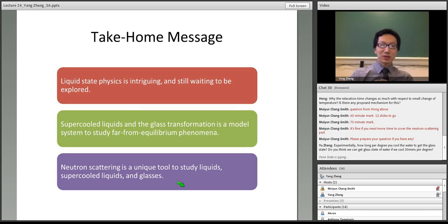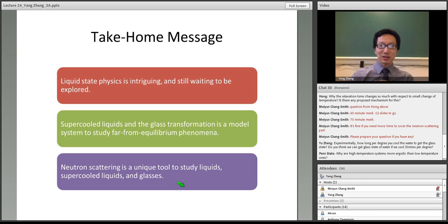So what we were doing is actually, since we just listened to Jin's nice lecture, we're trying to locate whether there's a second liquid-to-liquid critical point in water. Based on his theoretical predictions, the second critical point lies in the region of the phase diagram, the so-called no man's land, below the homogeneous nucleation. So there's no way for us to maintain supercooled water experimentally in that region. So we use nanopores. We can confine water in the nanopores. In other words, when we do that, water does not freeze in those conditions, and you are safe to do whatever cooling that you want.